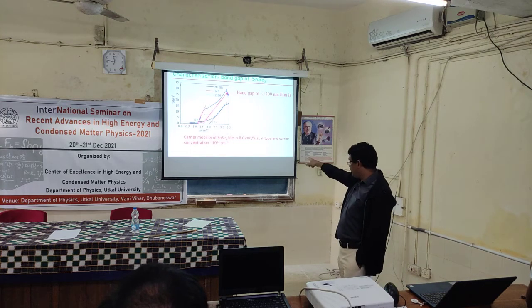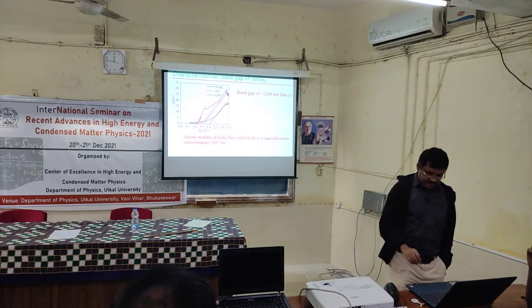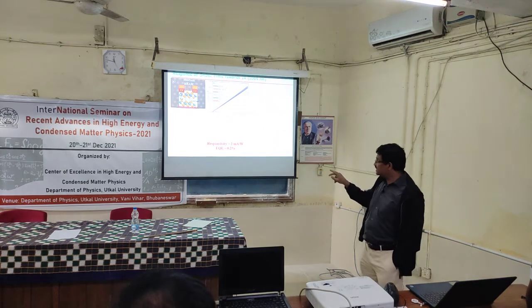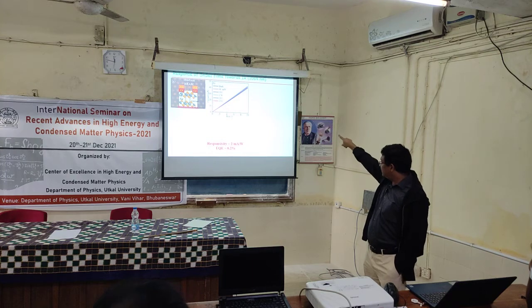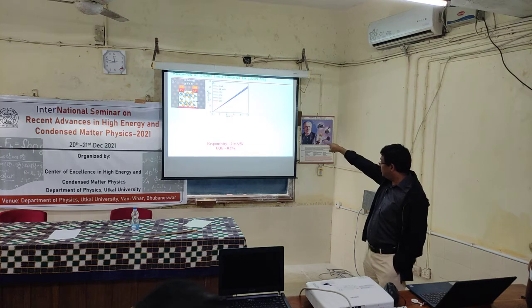So the bandgap for the 1200 nanometer film is like 1.2 electron volt, and we have done all measurements. We found that the carrier mobility is much lower than what is reported in the literature. We get about 8 centimeter square per volt second, and it behaves like n-type, with a carrier concentration of 10 to the power 17 per cubic centimeter. Then we take two contacts like chromium and aluminum or gold. The IV curve is linear. The lower curve is the dark one, and once you shine light, like 1064 nanometer, in the infrared region, at different powers, you can see there is an increase in the current.